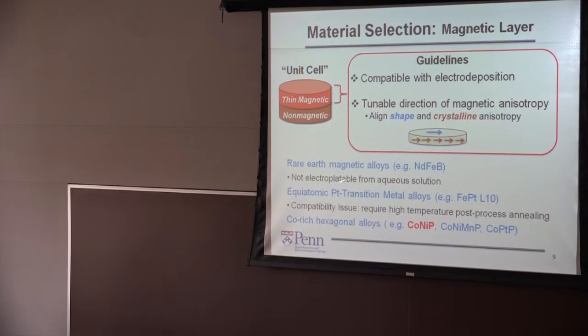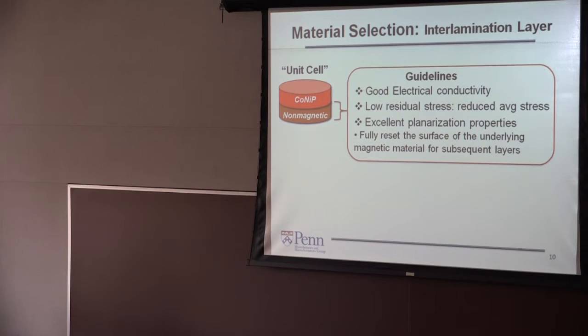There are lots of existing magnetic alloys. I won't go into the details of it. But if you want a CMOS-compatible and integrated fabrication approach, cobalt nickel phosphorus is one good choice. And this is the magnetic system that we used in this study. For the non-magnetic material, we call it the interlamination layer. Other than good electrical conductivity, we needed a very low residual stress, so that the average stress is reduced. We'll talk about this later.